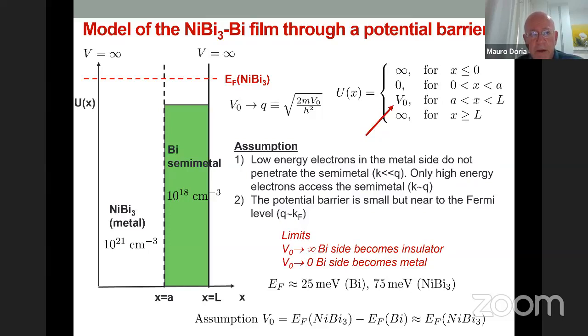Now for the model that we have done for nickel bismuth 3, we looked at a film with a potential inside here, which describes the bismuth. So electrons in the nickel bismuth 10 to 21, this is 10 to the 18. So we have to make it somehow more difficult for electrons to go into the bismuth region. So we introduced a potential with a new parameter V0 or Q, keep in mind Q, which measures the height of this barrier here, makes it more difficult for electrons to jump into the bismuth region.